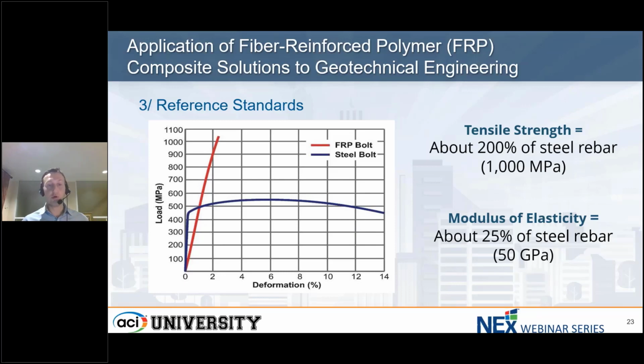behavior that is different. FRP, as we know, is a brittle material, meaning there's only an elastic phase in a stress-strain curve. That's why we have this red line here, characteristic of the FRP bar. So no yield point, no ductility, and therefore, while the modulus of elasticity is 4 times lower than steel, the elongation at ultimate is much lower. This is something we always have to remind, because the failure mode and the mechanism engaged in geotechnical applications are again different,